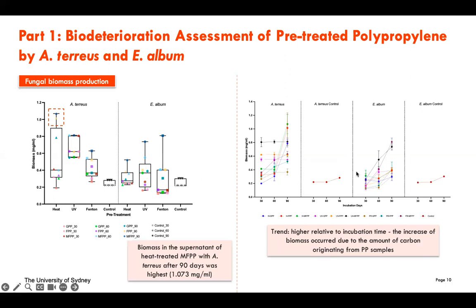When we compare to the control, the heat and UV treated polypropylene, regardless of its form, like film, metallized film, or even the granulated form, are shown to cause the fungi to produce higher biomass compared to the control. So this first indicator is actually very important, because we know that the higher the biomass produced, the more likely the fungi can grow and consume the polymers.